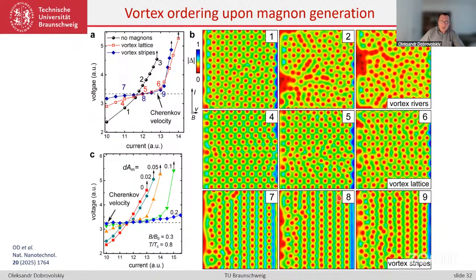So in all our relations, it turned out that not the hexagonal lattice formula should be used, but just a square lattice, where the periodicity is the distance between vortex rows, not on the basis of the hexagonal or triangular elementary shape. So the spin wave imposes a dynamic pinning landscape, and this landscape is then synchronized with vortices. Vortices are automatically phase locked because of the presence of the spin wave, which is generated because of their motion. So this is the condition of self-synchronization. Very interesting phenomena.